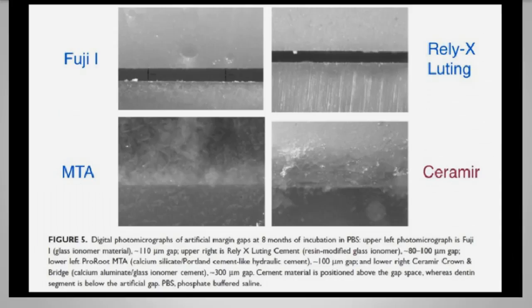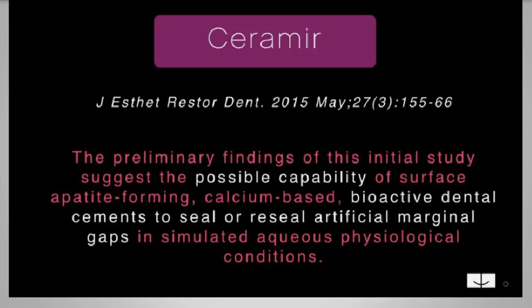Here's another one that shows at 8 months, right? At 8 months, here's the glass ionomer cement. Here's resin modified glass ionomer, because of course they're not bioactive. They can't form new apatite crystals. And MTA, this bioceramic material, and Ceramir can actually occlude. They can fill the gap. For me, that was the biggest selling point. I could not believe how important that was for me. That with artificial gaps, you could actually close the space with these new bioactive cements.